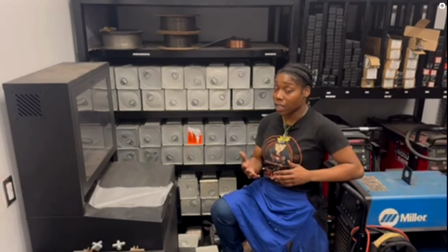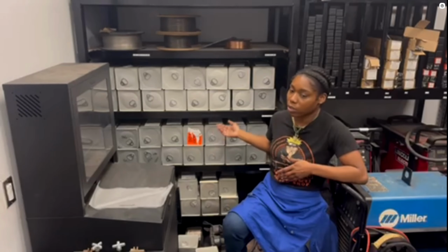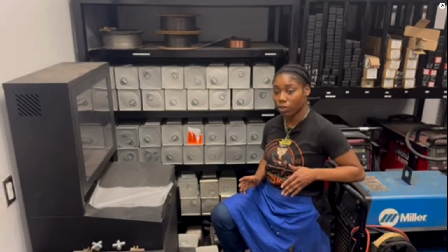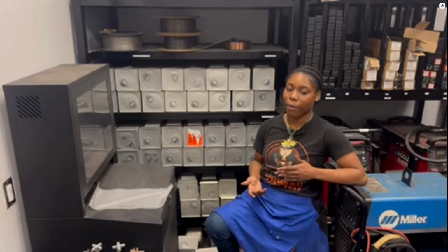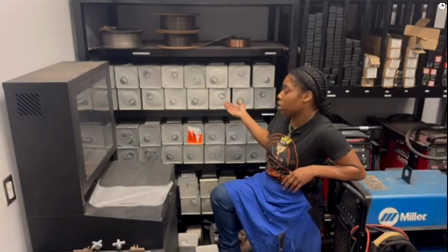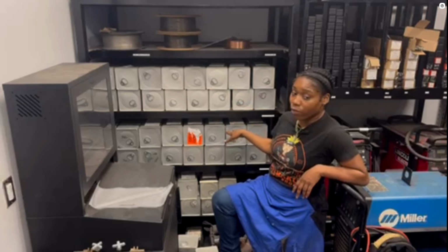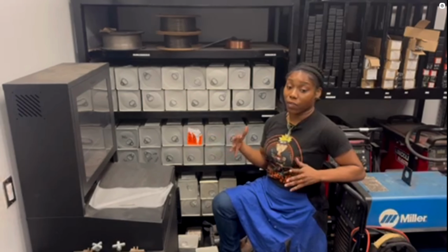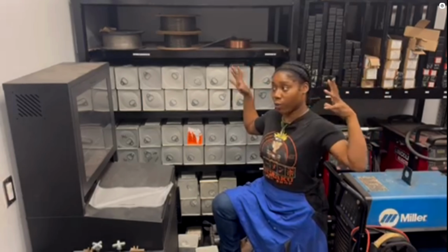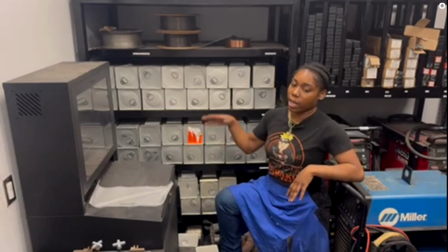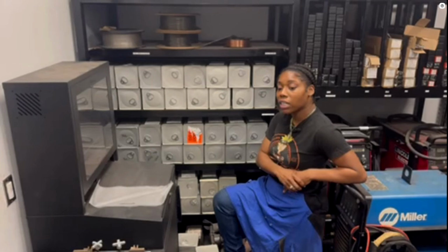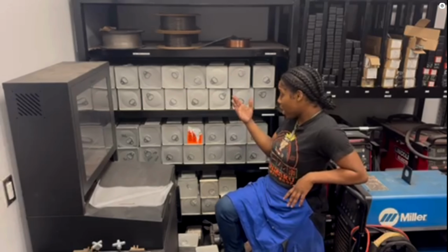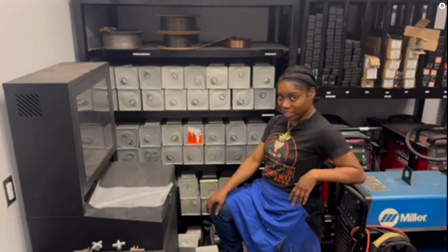So if there is moisture that is absorbed in it, we do have to rebake them at about 250 degrees to about 300 degrees for about an hour. We keep them in this dry area away from moisture. And if there is humidity in the atmosphere, which we don't really have, we can go ahead and put them in the oven at about 100 degrees to 150 degrees. And this is how we store and bake our electrodes.